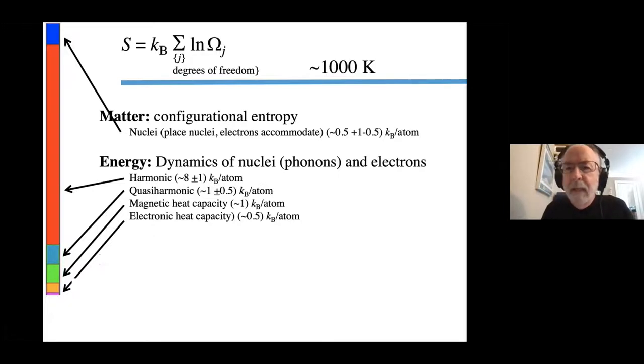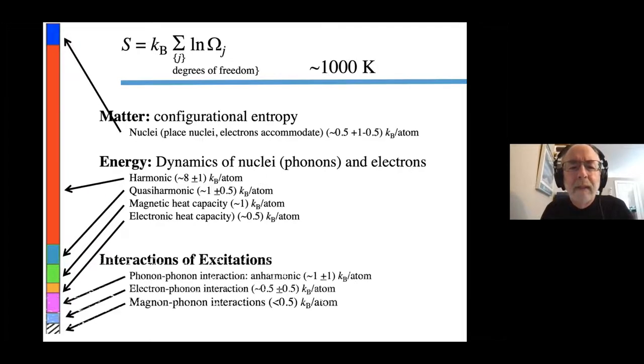The situation gets more complicated at 1,000 Kelvin, though, because these excitations start to interact with each other. The phonons, the cost to put them in, depends on how many you already have. And so that's an anharmonic effect with phonon-phonon interactions. But the same types of interactions are possible between the spins and the electrons too. And these contributions can be fairly big, and we need to get them right if we're going to do phase diagrams or get an accurate equation of state for a material.